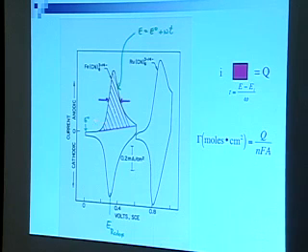We can also do the same experiment, but with ruthenium cyanide out in solution, and we get nickel ruthenium cyanide on the surface. It has a different redox potential, and so the whole peak shape is shifted more positive. You can see this isn't quite as clean out here. There's something else happening out there. That's the decomposition of the surface, the oxidation of the surface. You see our peak-to-peak separation is not quite 0, but it's a chemically modified surface, so you have to have a little flexibility here. And again, gamma is just that striped area, the area under the electrode, assuming that everything is redox active.